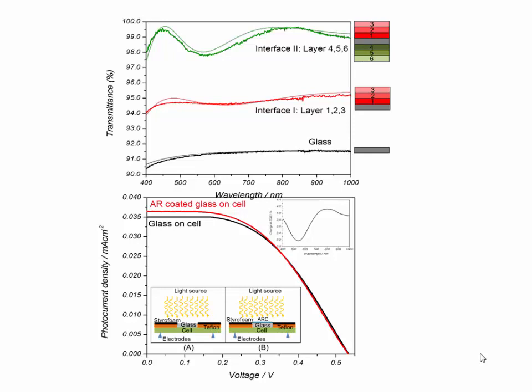Do you have a chance to investigate the polarization and angular dependence? Yes, I did, but I don't have the slides. I think the design was such that we actually managed to get like 97% for both sides, for both glass. For this particular anti-reflection design, we actually got like 96% average transmission. Sorry, I think that's a bit high. It's 95% transmission for an angular dependence for 0 to 80 degrees. So it's also quite broadband under oblique incidence.